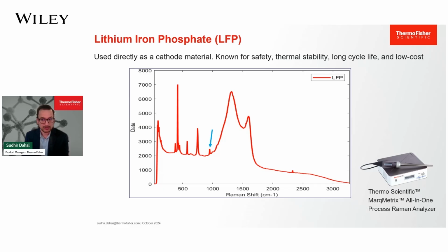The spectrum shown here was obtained using the all-in-one process Raman analyzer with the characteristic peak highlighted by the blue arrow. So Raman analysis, as shown in this example, allows for monitoring of specific species by examining peak positions and other characteristics of the spectrum. It provides these results almost instantaneously, often within seconds or minutes. And the rapid feedback facilitates quick monitoring and implementation of corrective actions, which can ultimately lead to significant savings in cost, time, and resources.